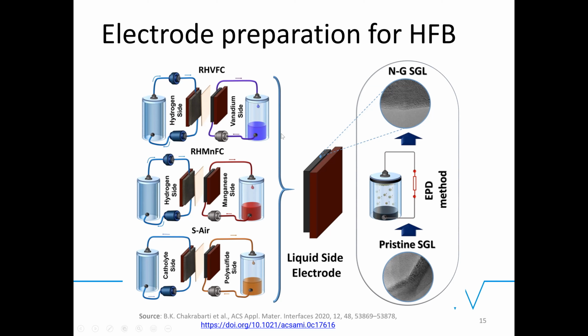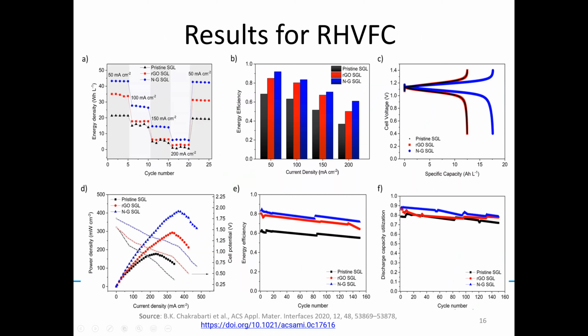And we compared three systems. The reason I'm saying SGL is that it is the manufacturer, a German company, of the carbon paper that we are using, and we have that as a background, and we modified that with reduced graphene oxide and nitrogen doped graphene. So the first results are for the hydrogen vanadium system.